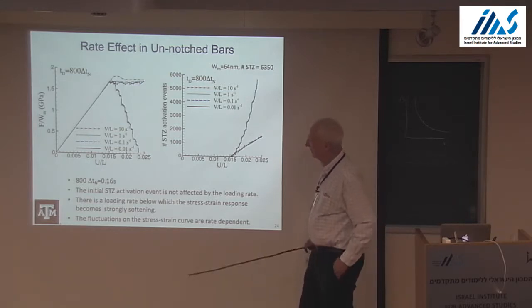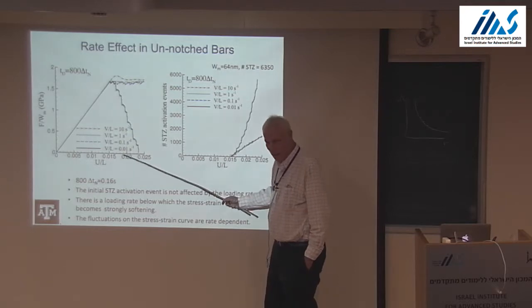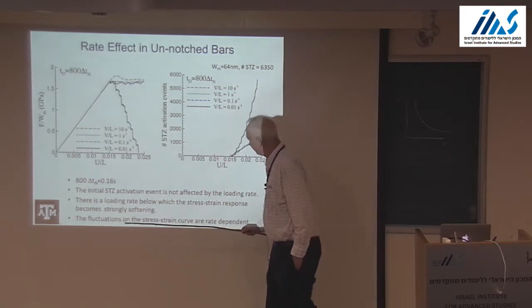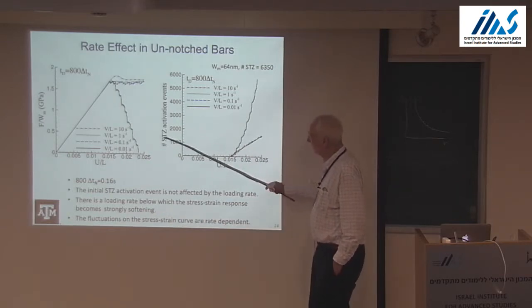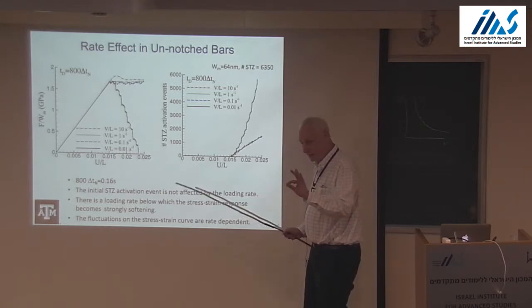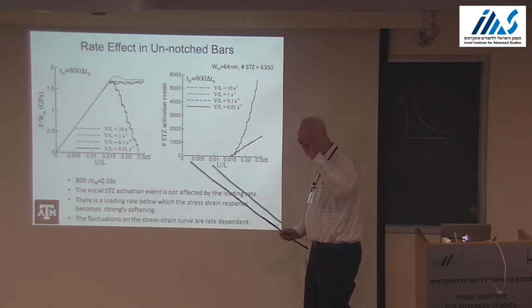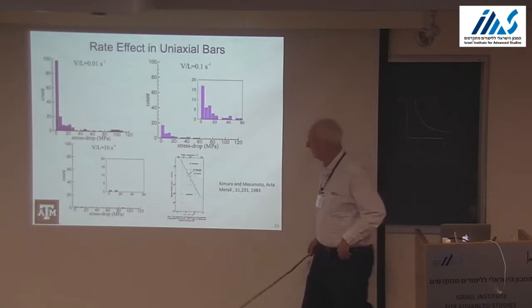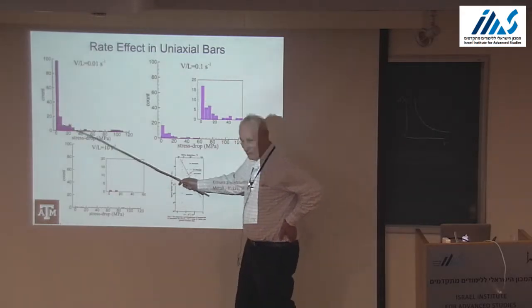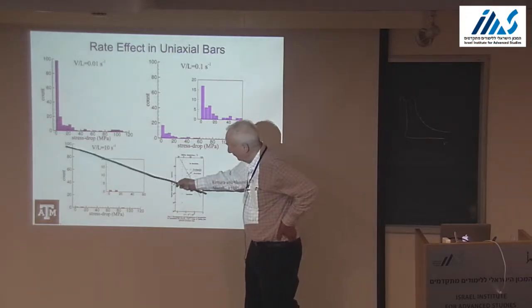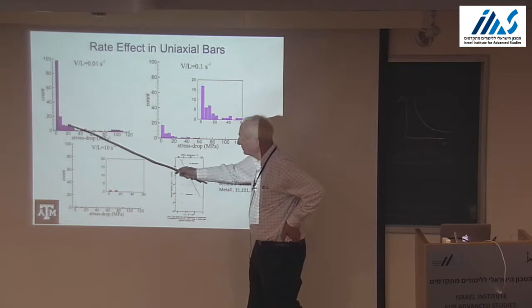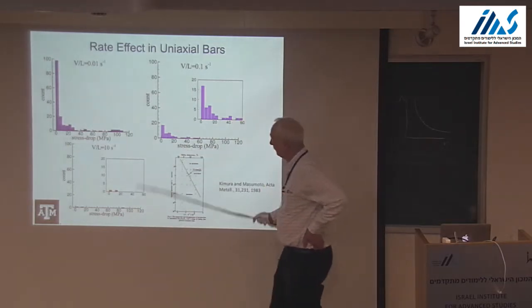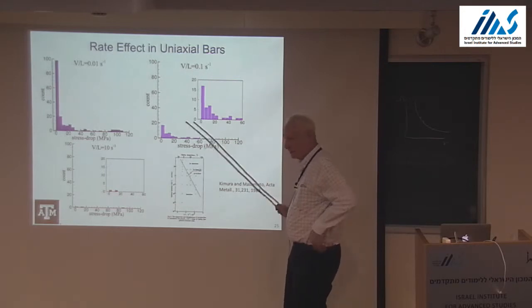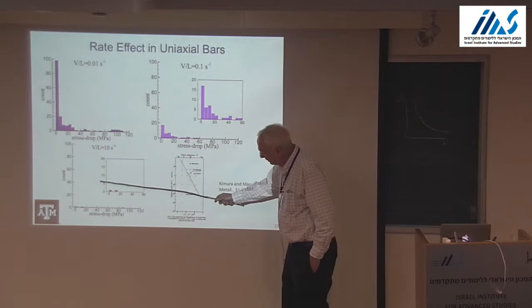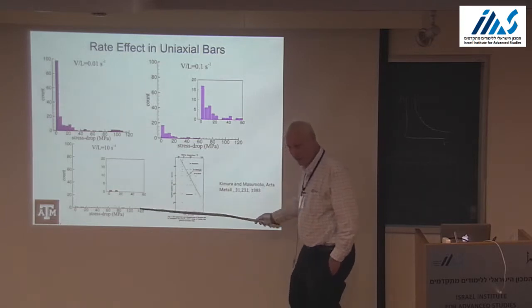We see a rate effect, and now we can do rates from 10 per second down to 100th per second. The slower the rate, the larger the drops we get, and the more fluctuations in the stress strain curve. We haven't done the statistics, but we can do histograms of the drops. And here you can see it: at 100th per second, lots of large drops. Go up to 1/10th a second, and the number of avalanches decreases. At 10 per second, it's nearly a smooth curve.